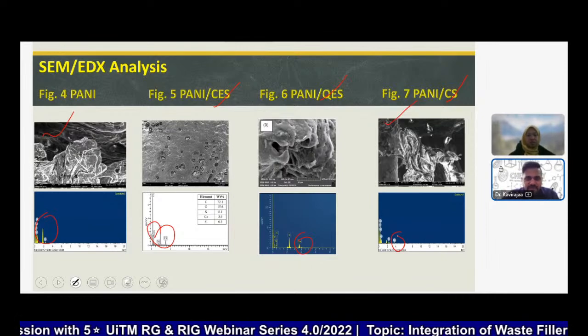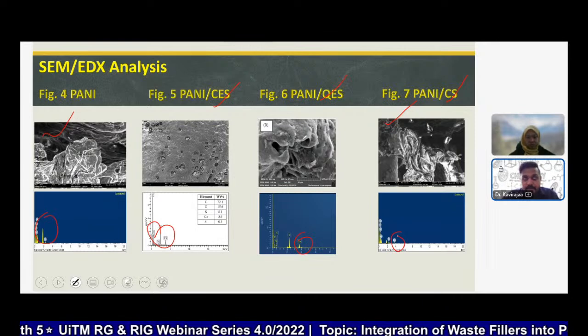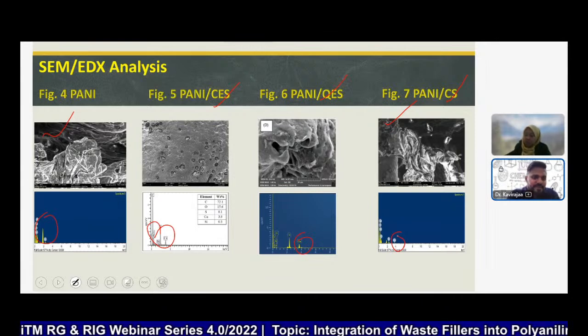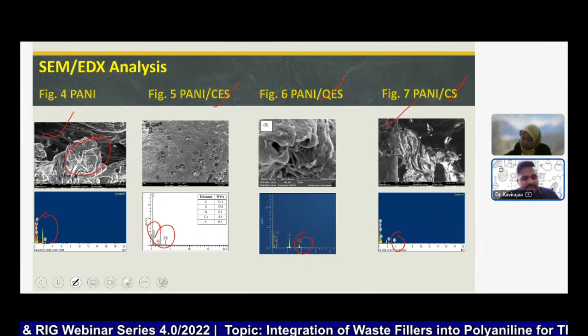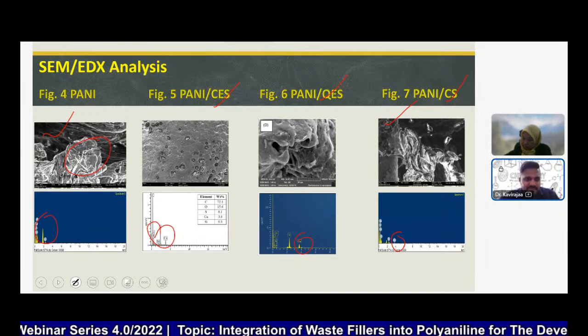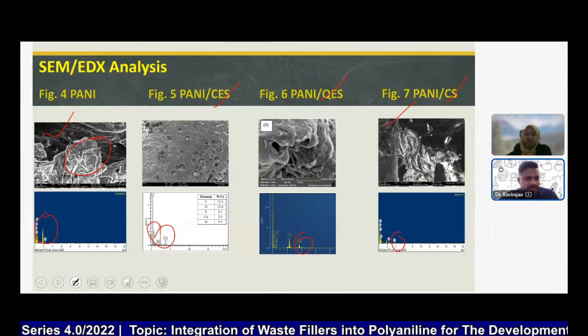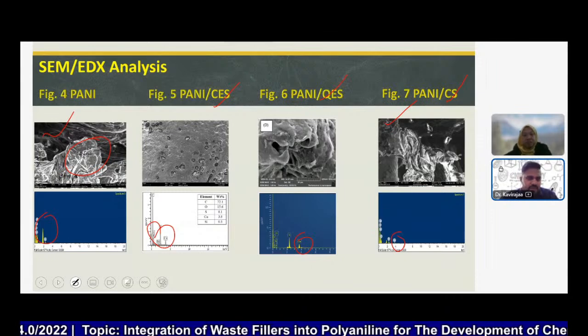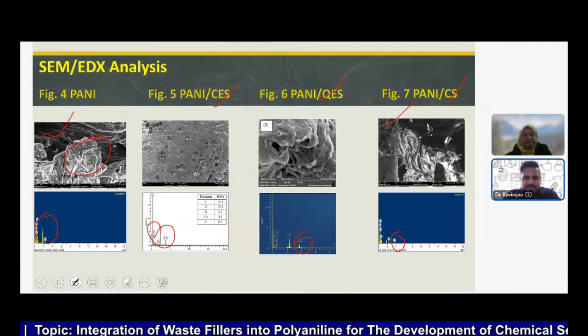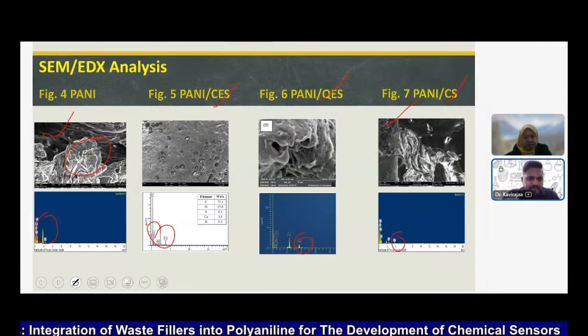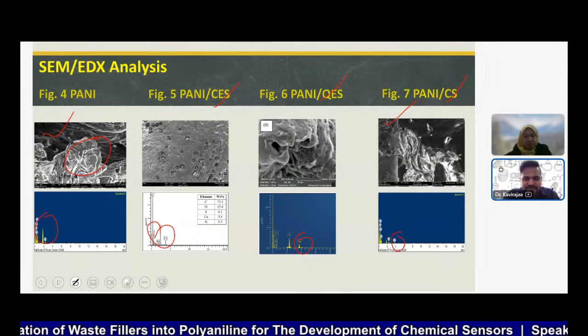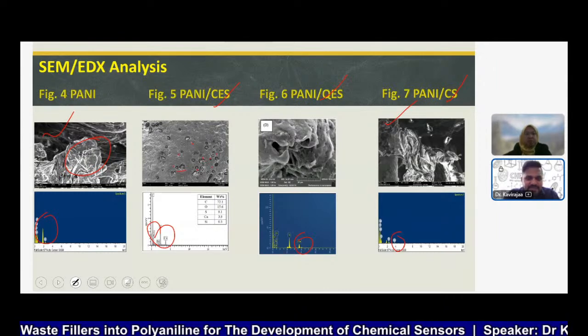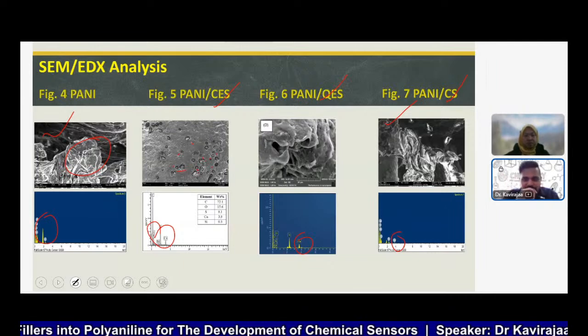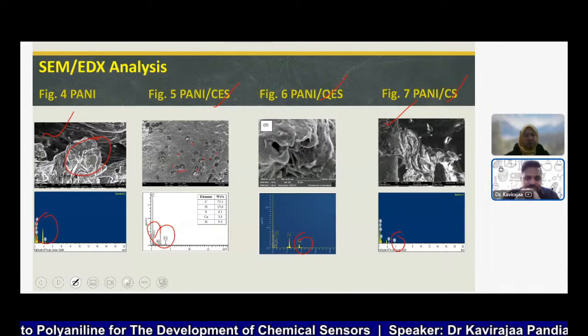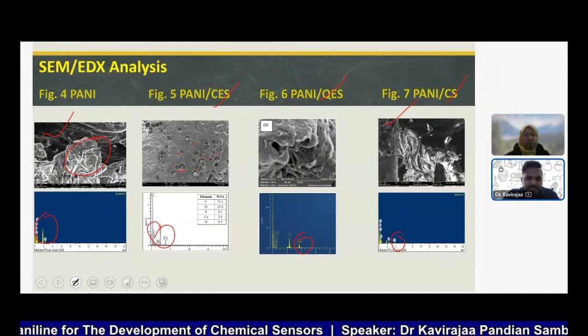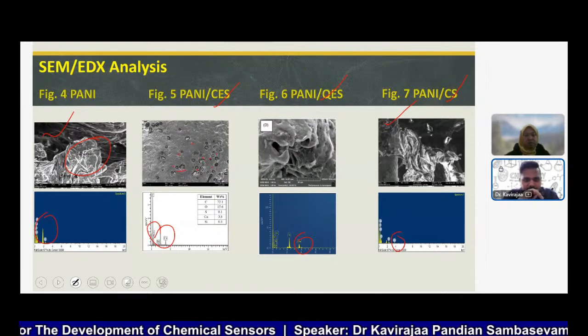When we look at the typical structure of these conducting polymer composites, we will get a flaky structure for the pristine PANI, or sometimes people might get globular as well, depending on the conditions that they control and so on. And for chicken eggshells, we don't see much improvement. We can just see that there is a certain degree of porosity here. Because we use submicron size chicken eggshells, maybe they entered the pores of the polyaniline matrix.